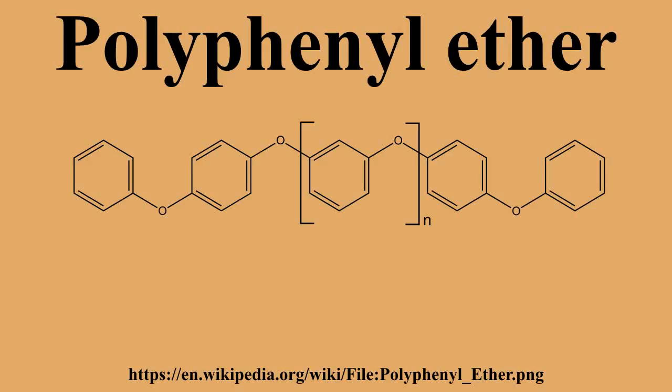Data presented in Table 3 demonstrates polyphenyl ether to be superior to other fluids that are commonly used in diffusion pumps. PPEs help achieve the highest vacuum of 4 by 10⁻¹⁰ torr at 25 degrees Celsius. Such high vacuums are necessary in equipment such as electron microscopes, mass spectrometers, and that used for various surface physics studies. Vacuum pumps are also used in the production of electric lamps, vacuum tubes, and cathode ray tubes, semiconductor processing, and vacuum engineering.